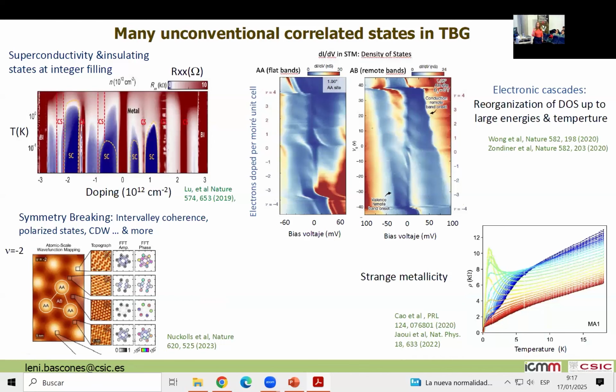One thing I'm not going to go into in detail is that the phase diagram of twisted bilayer graphene is much richer. Later I will show some of the states. It's much richer than Pablo saw in the first paper. There are samples in which you have seen several superconducting domes. For example, there are more correlated insulating states. People have observed a lot of different types of broken symmetry states. There are fascinating reorganizations of the spectral weight, changes of the density of states as a function of doping, that are called cascades. And there is also a region in which the resistivity depends linearly on temperature, that is telling us that our system is interesting in terms of what the correlations are doing, and this type of property is also seen in the cuprates.